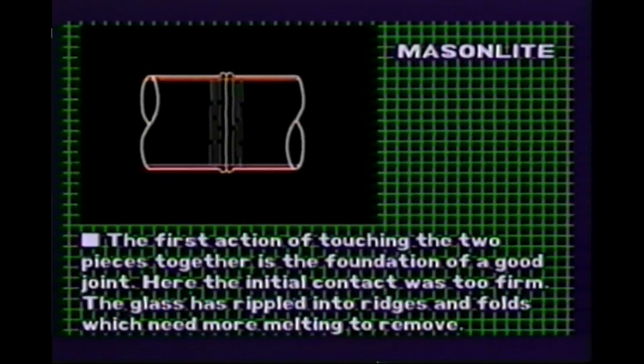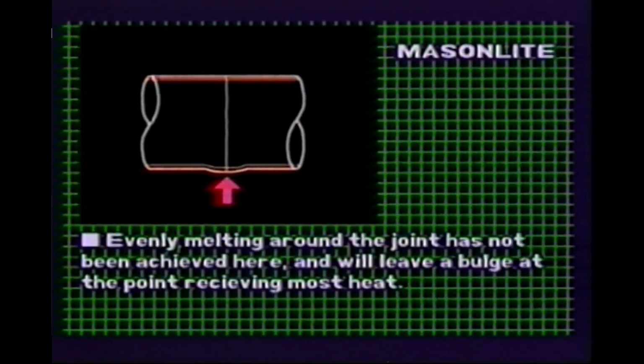Most of the faults associated with joints or splices are a result of the melting and blowing of the glass. The first action of touching the two pieces together is the foundation of a good joint. Here, the initial contact was too firm. The glass has rippled up into ridges and folds, which require more melting than normal to remove. Evenly melting right around the joint has not been achieved here, and will leave a bulge at the point receiving most heat.